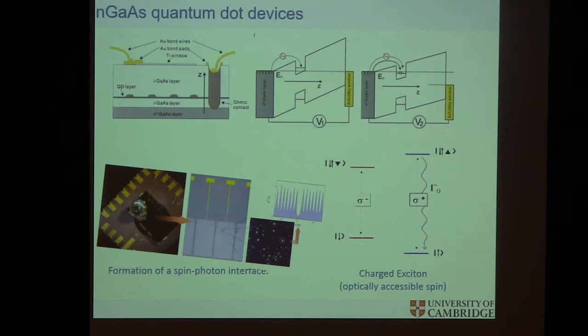This is what it looks like. So that's the chip of gallium arsenide with a layer of quantum dots embedded. These are the contacts, these guys. And right on top of it is one big blob of solid immersion lens. It's a hemisphere that's literally glued on top of the sample. That's our fabrication capabilities at the moment. We can do waveguides, we can do other stuff, but anything we do with these self-assembled quantum dots reduces their quality. So it turns out that for most of the experiments, by simply putting a hemisphere of zirconia on top, it worked well enough.